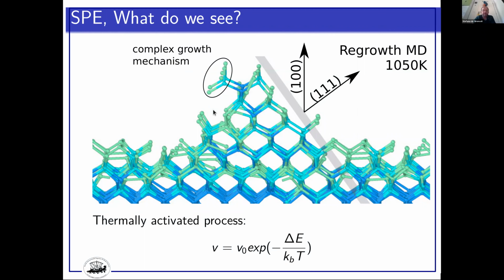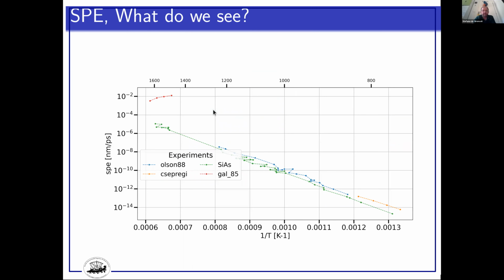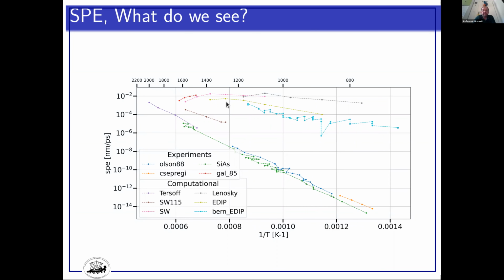All the process is associated with some activation energy, and so we can extract the activation energy from the simulation, which is compatible with our simulations. The experiment gives a certain velocity of the recrystallization that follows an Arrhenius plot, as a function of inverse temperature, and models are everywhere, basically, and our data are here. So we get the right slope.